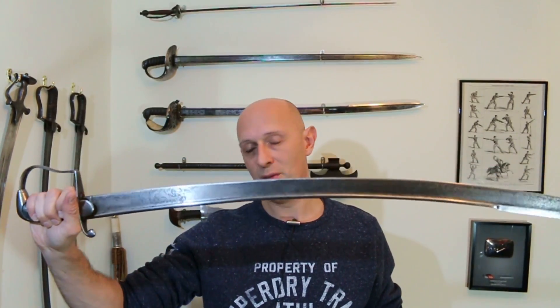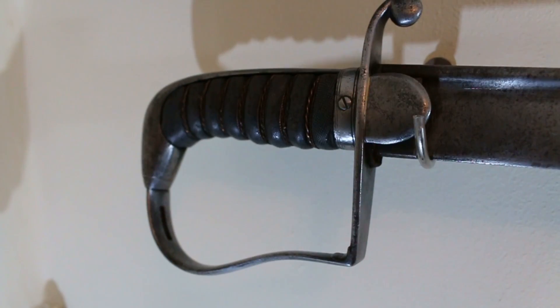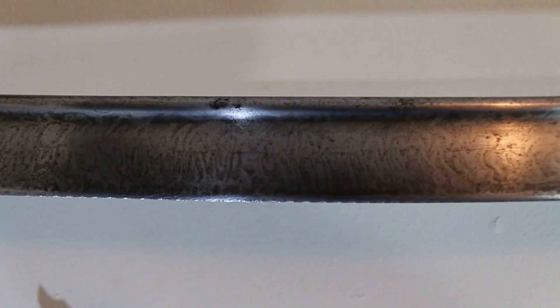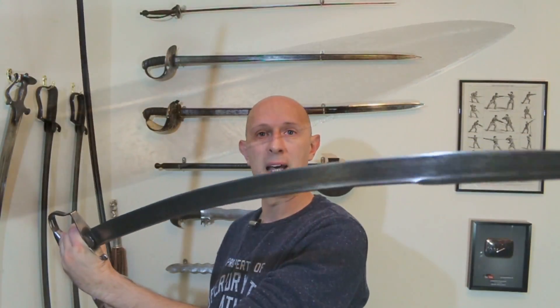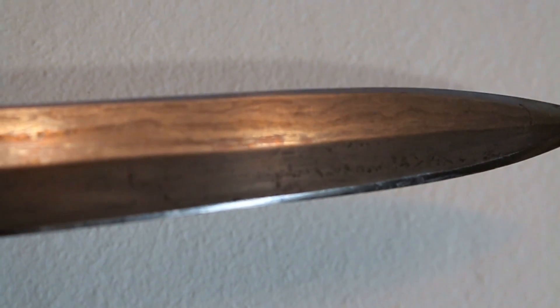Here's a sword I'll be talking more about soon — and that Bavarian sword as well. This one has actually got a pattern etched on the blade: this is etched Damascus. So something we find on German-made swords is Damasteel, meaning Damascus steel — or actually what they mean is pattern welded steel — or Echt Damask, meaning etched Damascus. They've painted with acid a picture of what looks like pattern welding, or even Wootz, onto the blade. Up here we have a blade made of at least two different types of steel forge welded together into a pretty pattern — that is pattern welding.